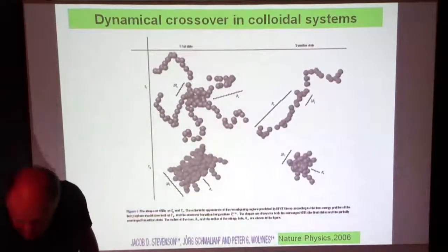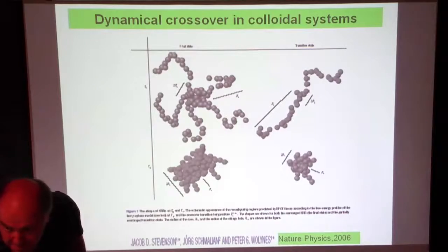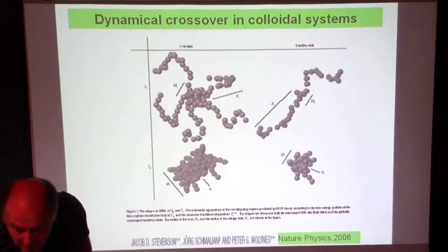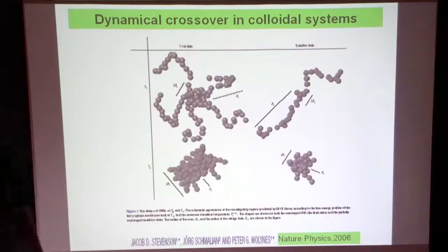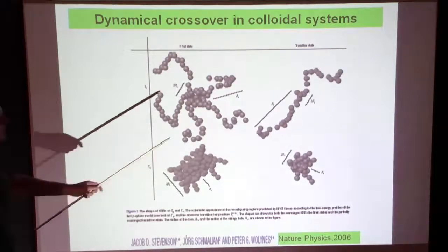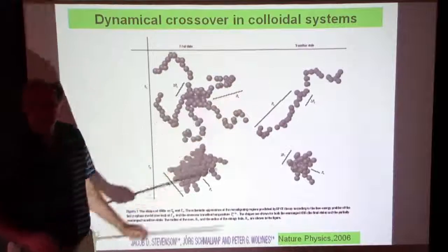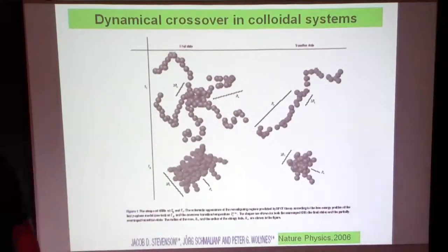And since this kind of barrier represents more like an entropic barrier than an energy barrier. That's a good point. We talk about right now only about energy. Why is there no entropic point? Actually, we can come to that also. That's a very good point. But the thing that makes this take a long time is not because there's an energy barrier to it. In fact, there's very little energy barrier to move along a string, right? What makes this take a long time is that they all have to line up.